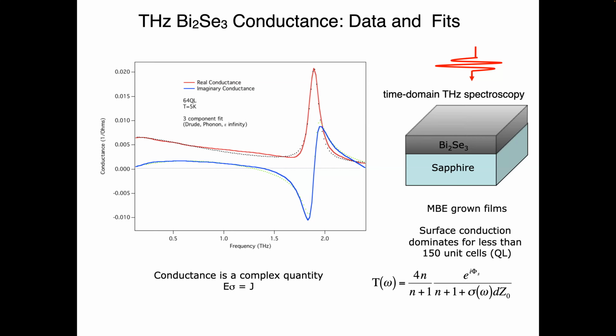Very often what we're going to do is measure some frequency range, real and imaginary parts, with time domain terahertz. And then we're going to use that complex information to learn about parts of the spectrum that we don't actually measure. Okay, that sounds maybe like magic, but that's of course what we do, and that's the example I gave yesterday, when you measure the superfluid density in a superconductor. You're not measuring the delta function, because that's just infinite conductivity. You're measuring somewhere else and then learning about it.